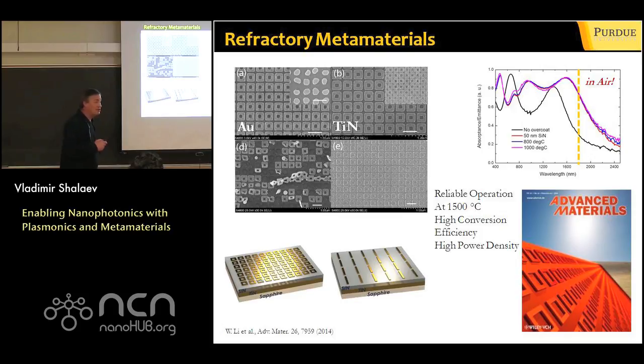And as for the frequency selective emitter, you could use simple rods like shown here. And they would emit in the spectral range matching the photovoltaic cell. That's really important, that the match is good. And to show that titanium nitride indeed is advantageous over gold, we made this rectangular ring out of gold and simply heated it up here to 800 Celsius.